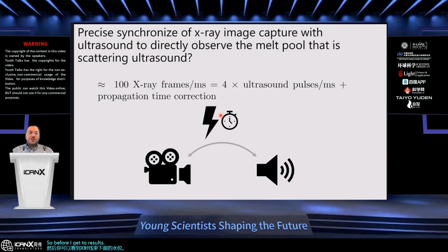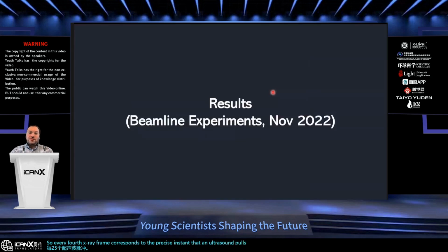So before I get to results, I want to make one note about timing and synchronization. We're doing this at the Advanced Photon Source, the X-ray facility, so that we can actually see the melt pool, and we can see the melt pool at the instance that the ultrasound wave reaches the melt pool and scatters. And so we have the ability to map the ultrasound signal through the X-ray extremely precisely, right? So in these experiments, we're doing 100 X-ray frames for every 25 ultrasound pulses, right? So every fourth X-ray frame corresponds to the precise instant that an ultrasound pulse reaches the melt pool.